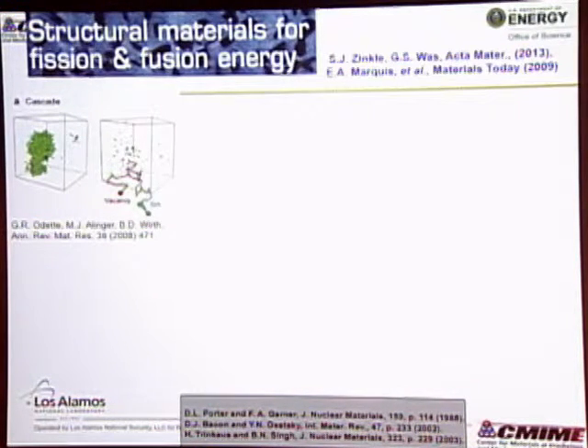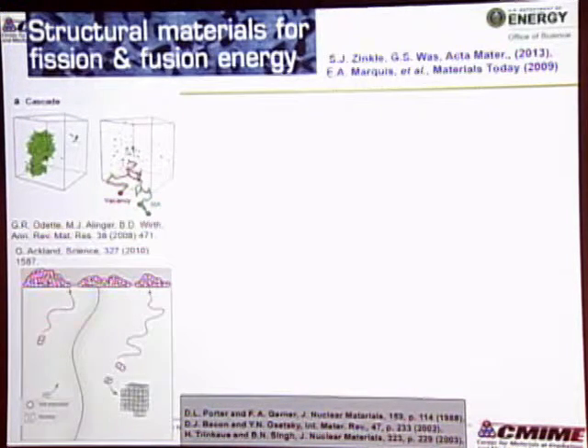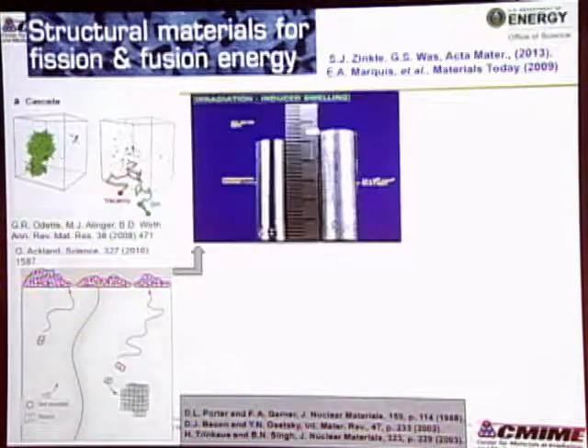Now, after that cascade happens, all of these atoms sort of rearrange, and you'll have a few defects in the end. Some of them are called point defects, called vacancies. Some of them are called interstitial atoms. And what happens is that these vacancies can move around within the material, and if they coalesce like this, they form voids. And of course, voids are bad.